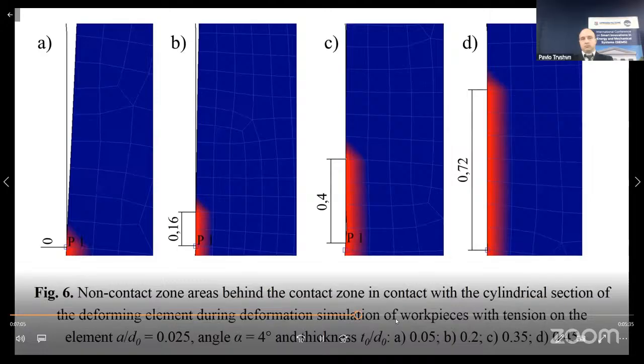To confirm this fact, consider figure 6. As follows from figure 6, which shows the areas outside the contact zone after the tool working on a thin-walled workpiece, figure 6a, there is no contact of the cylindrical belt with the machined surface. As the thickness increases, the contact pressure increases, which causes the appearance of an axial flow of the processed material from the contact zone to the non-contact zone.